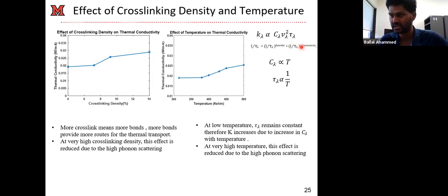Anharmonicity means that when you increase the temperature, in the ideal phonon picture, the atom vibrates at the bottom of the potential well to and fro. But when you increase the temperature, its energy level gets shifted from the bottom of the potential well to higher. So now the potential well is no more symmetric, it is more asymmetric. That is what is related to the anharmonicity. I mean, the potential well is no more harmonic, no more parabolic.